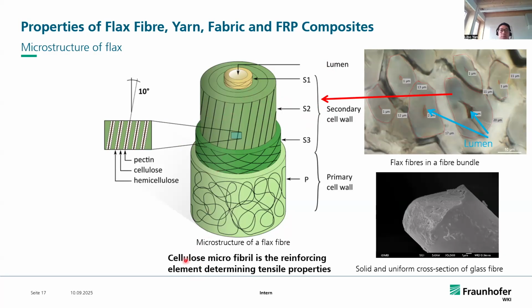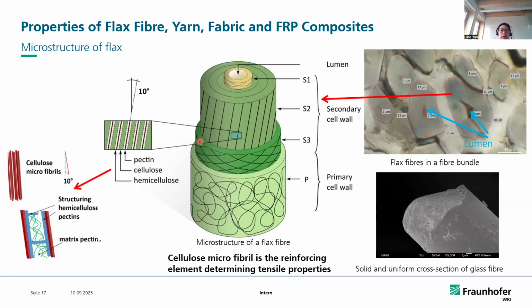Those microfibrils are further oriented with an angle around 10 degrees with the longitudinal direction of the fiber. This microfibril angle also determines the mechanical performance of the fibers significantly. In general, if a plant-based natural fiber has a smaller microfibril angle, the tensile strength will be higher. Otherwise, the tensile strength will be smaller.